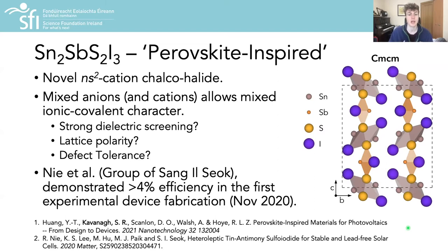The aim is replicating the high performance of lead-based perovskites while avoiding the presence of lead and achieving a commercially viable level of stability. Chalcogen halides are ideal for this goal as metal chalcogen bonds are much stronger than metal halide bonds, affording greater thermodynamic stability in this material class.